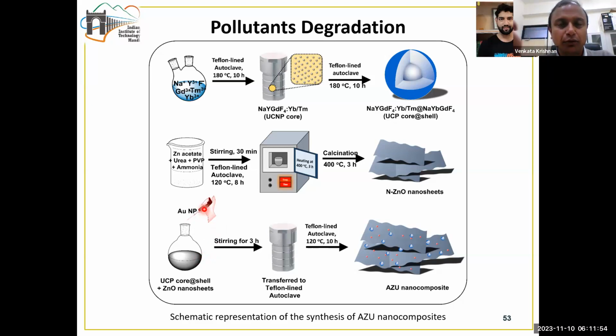because we do not need a lot of gold nanoparticles. We just need 2 weight%. We mixed them all and then stirred them for about 3 hours to ensure that they are very well mixed. Then we transferred the mixture to the hydrothermal reactor, which is this Teflon-lined autoclave, and heated it in an oven at 120 degrees C for a 10-hour duration, to end up with this composite.